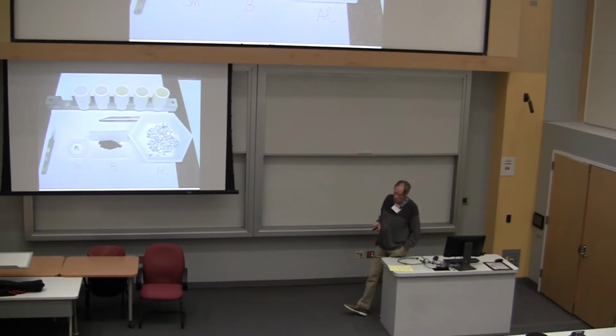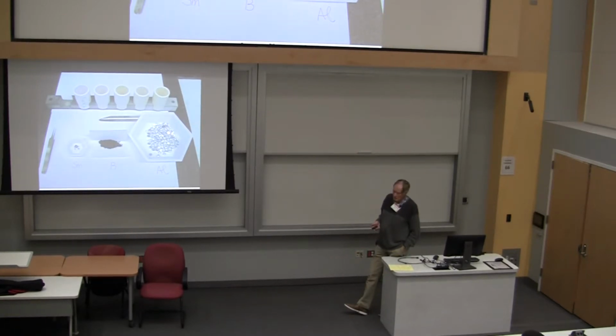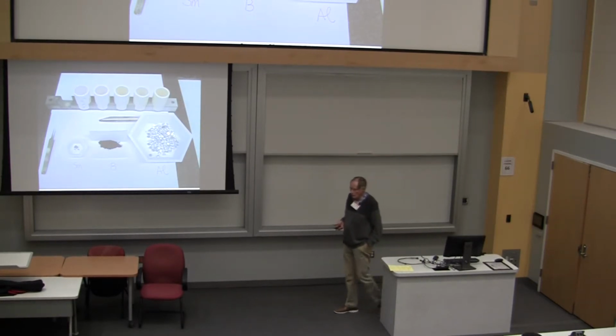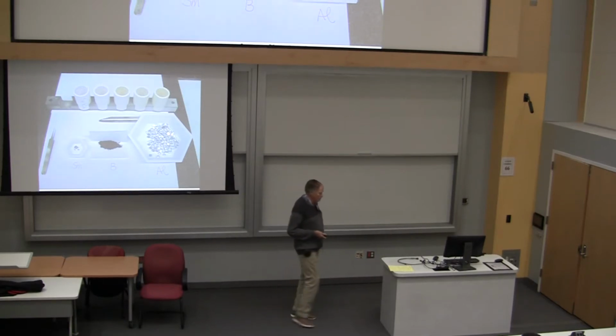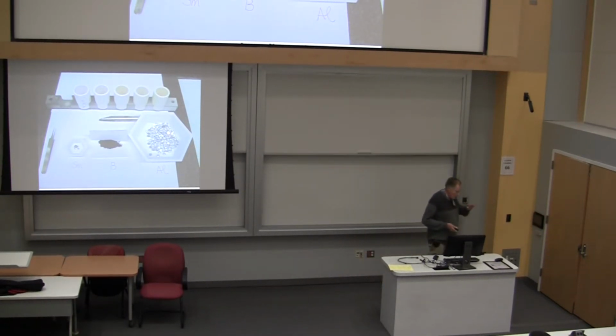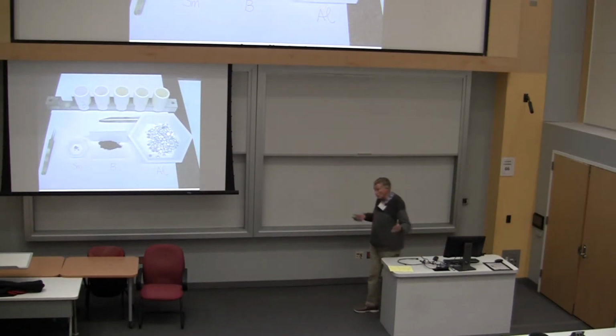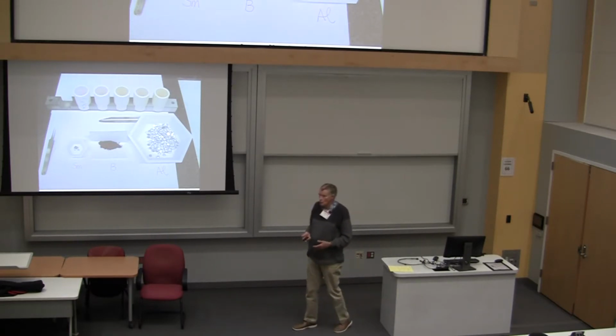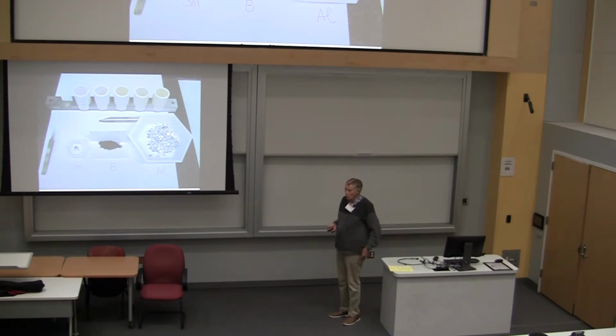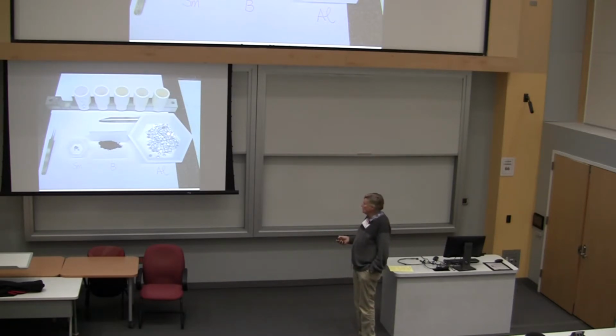But I took lanthanum B6, made it, and heated it up in an alumina crucible with some aluminum and let it sit at 1200 degrees for a while to see how much the weight of the pill of lanthanum B6 changed. And as I remember, 13.6 milligrams of lanthanum B6 are soluble in 1 gram of aluminum at 1200 degrees. So the typical growth for these hexaborides is that you have a 50 ml crucible in which you put between 50 and 70 grams of aluminum, and the total SmB6 amount here is less than a gram, maybe 600 milligrams.